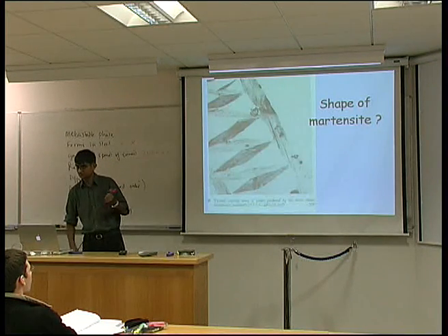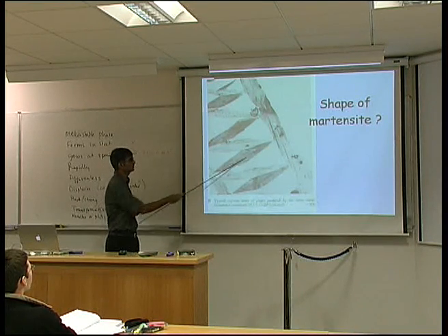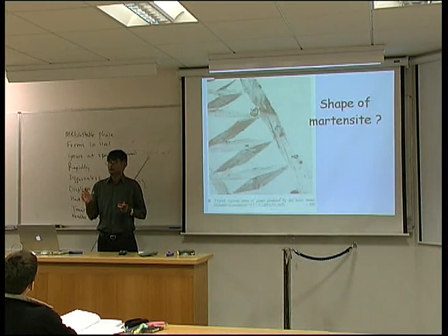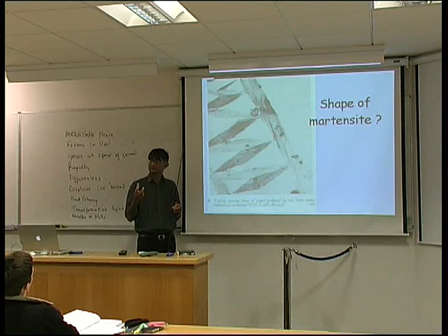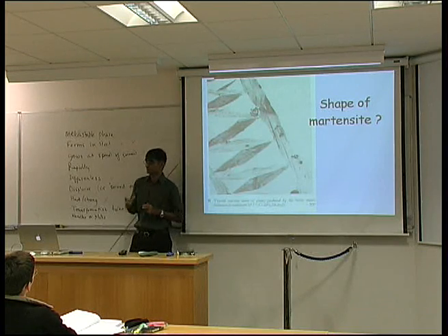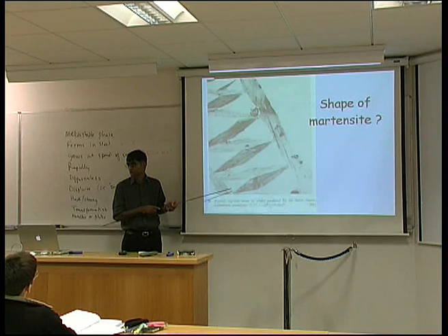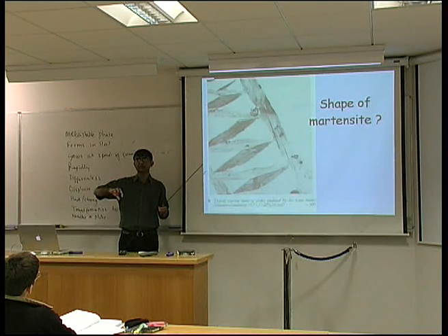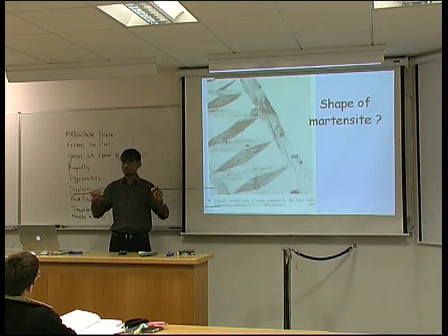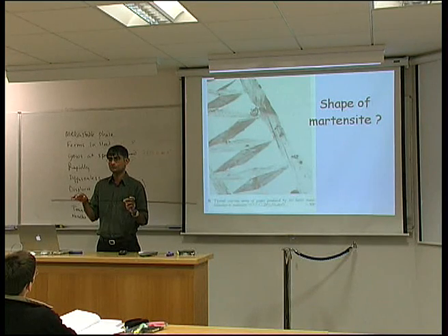And when we look at martensite in an optical microscope, indeed, it looks like plates which are sharp at the end. I'm afraid the idea that it's needle-shaped is not correct. Okay, now, what are the consequences if martensite is needle-shaped? We would be able to observe sections which are almost circular or elliptical, etc. And we don't see that. You see all of these as plates. So these are sections of plates in three dimensions.